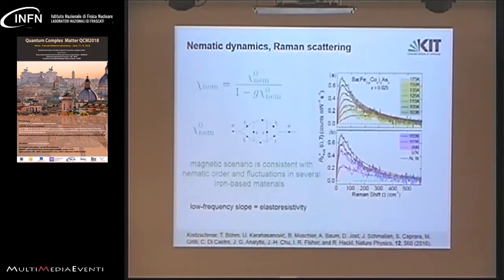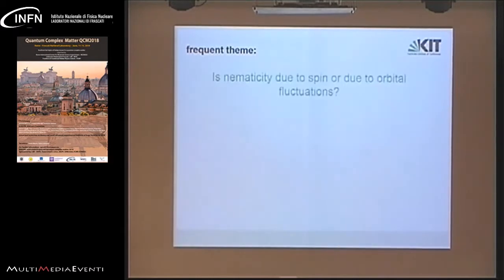You can even go further and look at this magnon coupling or spin excitation coupling in more detail. We did this here in a collaboration with the Rome group, Marco Grilli and Carlo Di Castro, and experimental data by Rudi Hackl, where you can fit quite quantitatively and in great detail the Raman response based on this specific nematic scenario that uses magnetic excitations to drive this symmetry broken state.